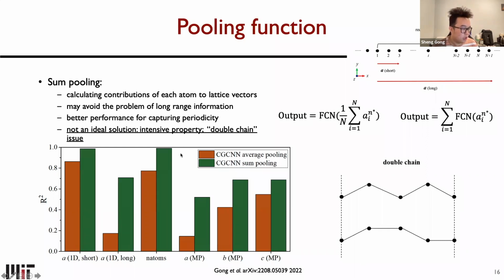But here we want to say that sum pooling is not an ideal solution to the problem of capturing periodicity due to 2 reasons. The first reason is the presence of intensive properties, just like thermal conductivity or electron conductivity we mentioned before, where we cannot use sum pooling because we have to keep the supercell size invariance. And the other reason is that periodicity is actually not an extensive property, and we can design some toy cases to fool sum pooling.